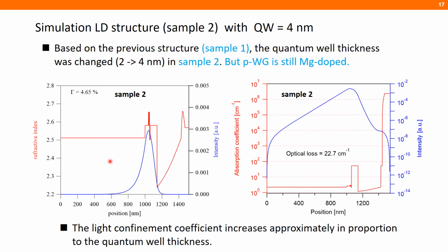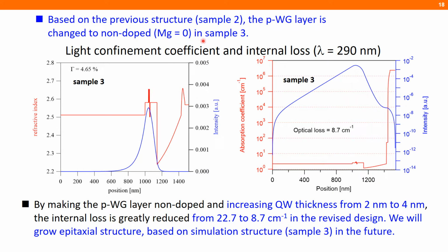What we tried to see was the gain. Here is the refractive index data, and here is the absorption spectra. With magnesium doping of the P waveguide side, the optical loss was 22.7 centimeter inverse. So it was very high. So what we did, first we changed the waveguide. We rearranged the waveguide, and also removed the magnesium doping from the P waveguide, and we could reduce the optical loss from 22.7 to 8.7. So this structure is very nice, and the optical confinement factor of 4.6% was achieved through simulation.